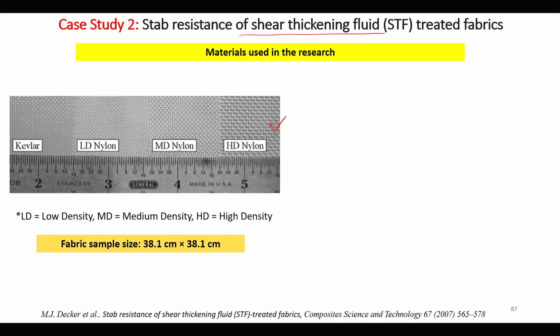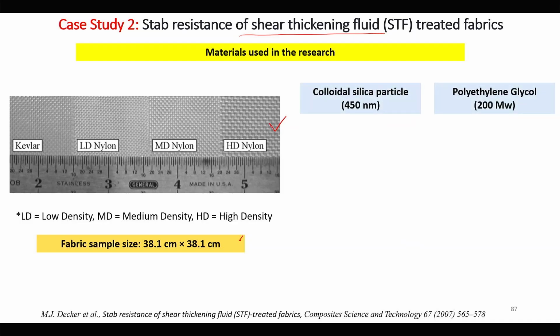The fabric specimen size is 38.1 by 38.1, and colloidal silica particles of 450 nanometer and polyethylene glycol were used, and STF is prepared.